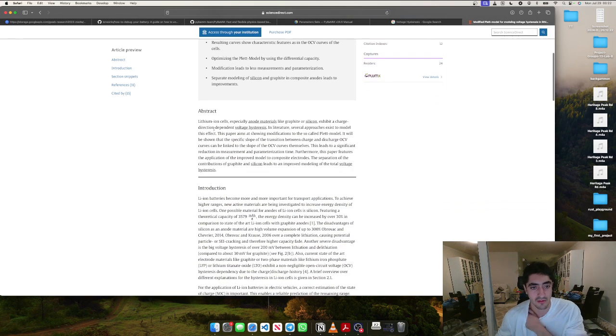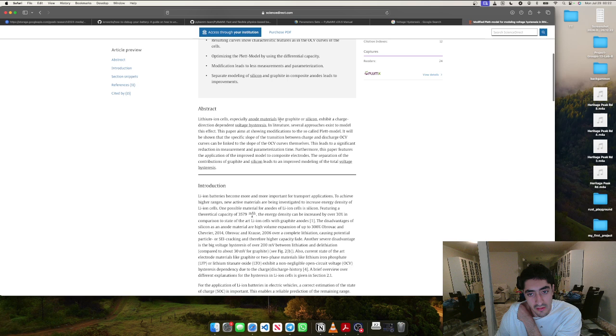First order abstract. Okay. Lithium-ion cells with anode material like graphite or silicon exhibit a charge direction dependent voltage hysteresis. In literature, several approaches exist to model this effect. This paper aims at showing modifications to the so-called Plett model. It will be shown that the specific slope of the transition between charge and discharge OCV curve can be linked to the slope of the OCV curves themselves. This leads to a significant reduction in measurement and parameterization time. Furthermore, this paper features the application of the improved model to composite electrodes, the separation of the contributions of graphite and silicon. Okay.